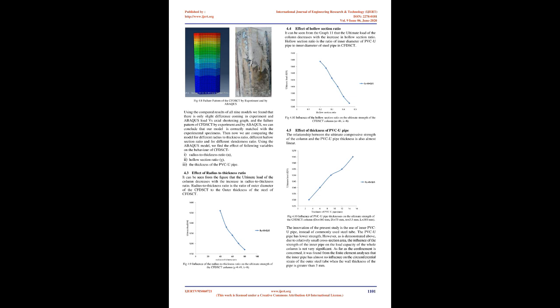Using the compared results of all 9 models, we found that there is only slight difference between the experiment and ABAQUS load versus axial shortening graph, and the failure pattern of CFDSCT by experiment and by ABAQUS. We can conclude that our model is correctly matched with the experimental specimens. Then now we are comparing the model for different radius to thickness ratio, different hollow section ratio and for different slenderness ratio. Using the ABAQUS model, we find the effect of following variables on the behavior of CFDSCT.